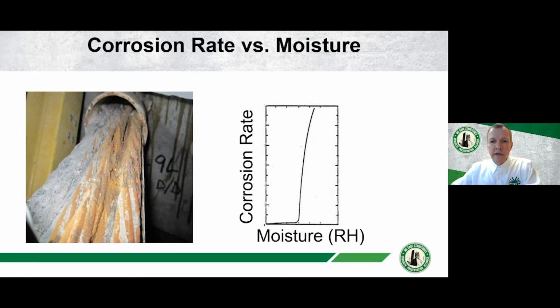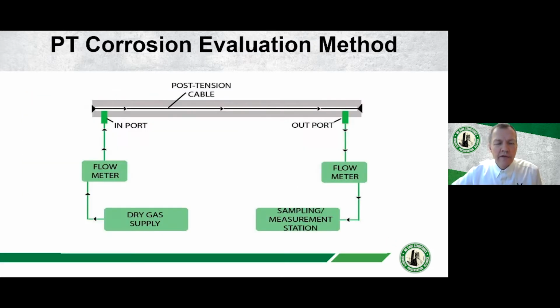If you know that, then you can take that information, and we use that relationship in a corrosion evaluation technique that we have. We call it PT corrosion evaluation. It's not a very innovative name, but it is a very useful technique. And with this technique, we typically make two openings into the duct. These can be small drilled holes, or they can be larger, depends on what you want.